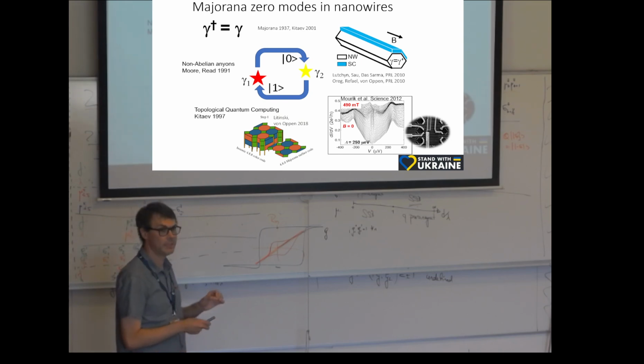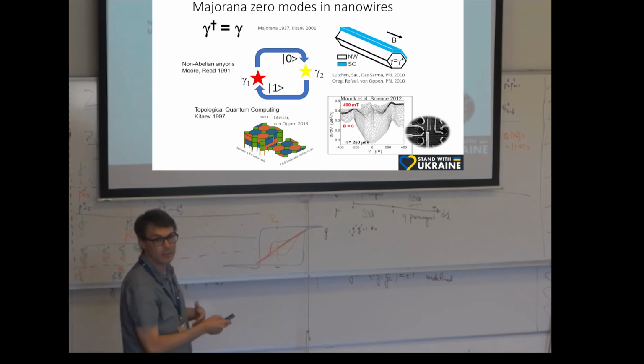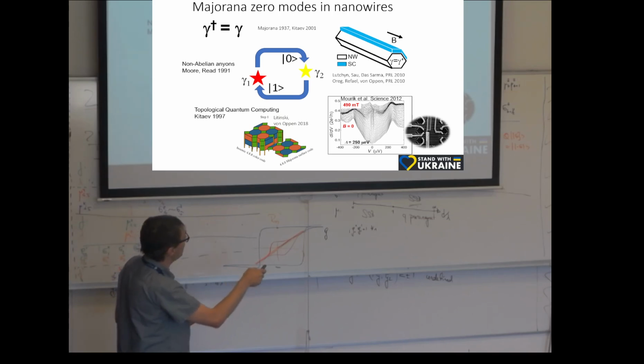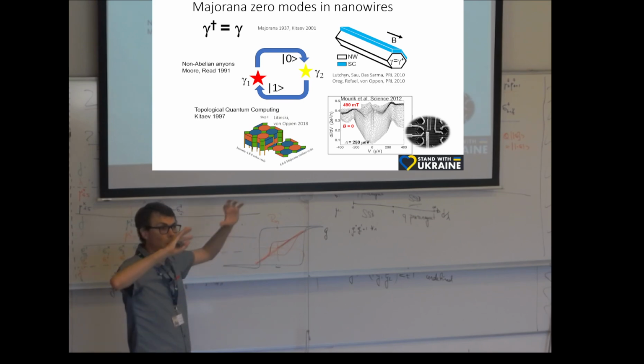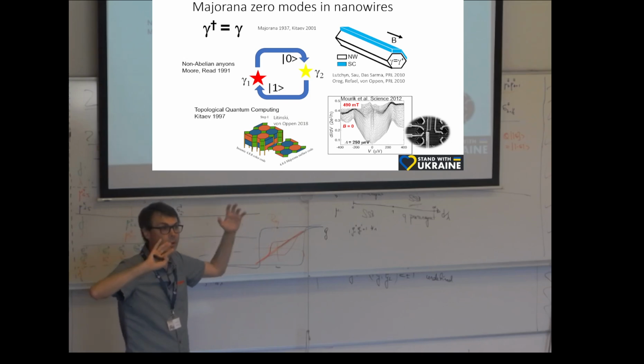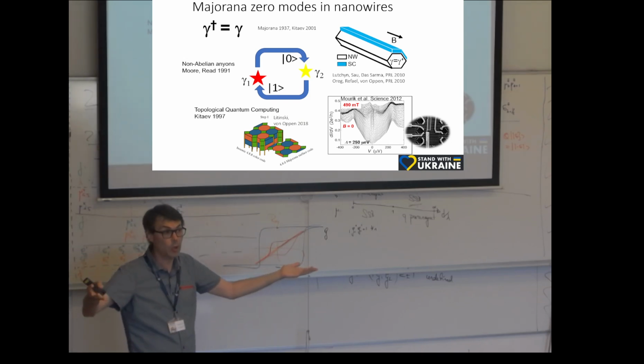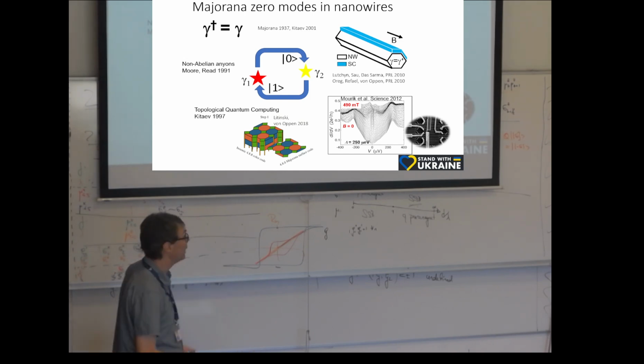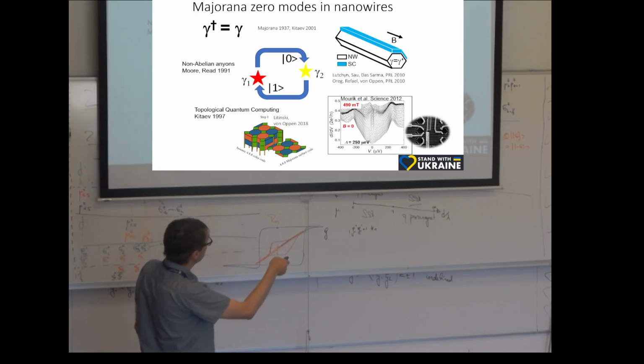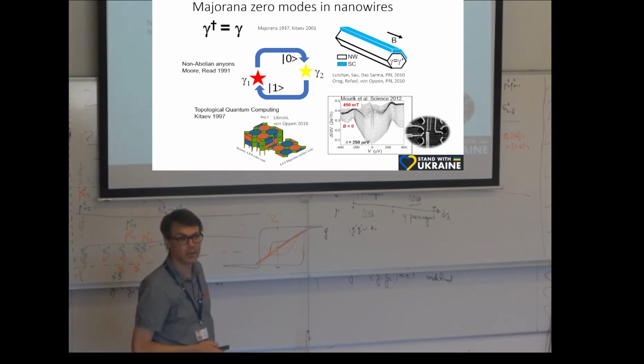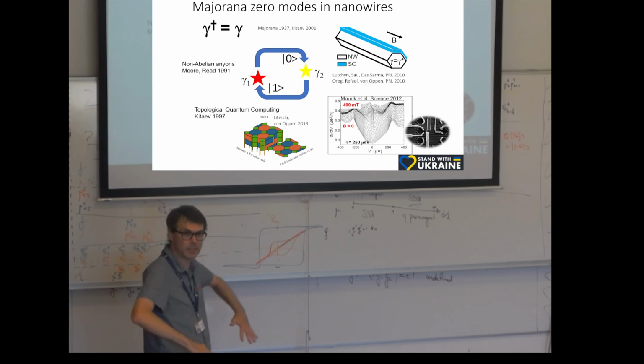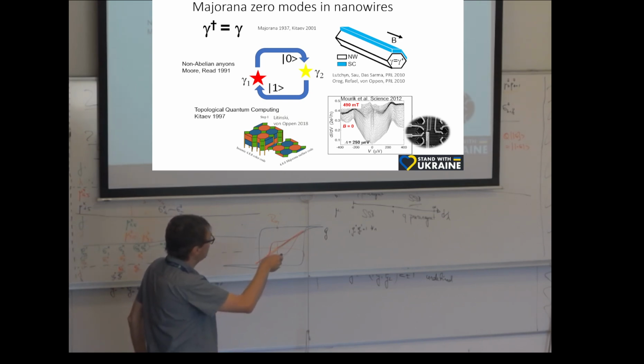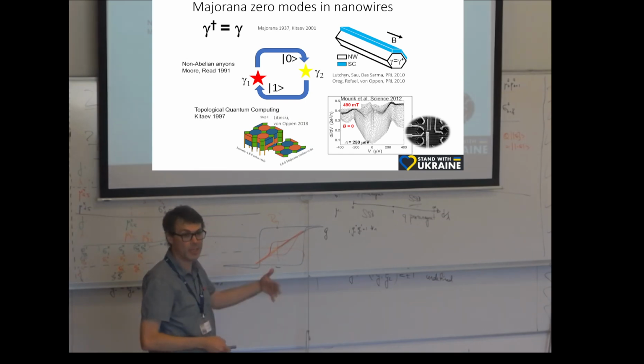And this is just sort of, can we establish the evidence that these quantum states are even present in these wires? And to do that, the starting point seems pretty easy. You put a nanowire, a semiconductor crystal, coated with a superconductor like aluminum, very conventional. And semiconductor is also well-known material, right? CMOS and other things, lasers. And what you're supposed to see is a little feature in the middle of this spectrum, a superconducting tunneling spectrum. These little ears are the superconducting gap, and inside the gap, in a suppression, there should emerge in magnetic field this feature, and that's called the zero bias peak.